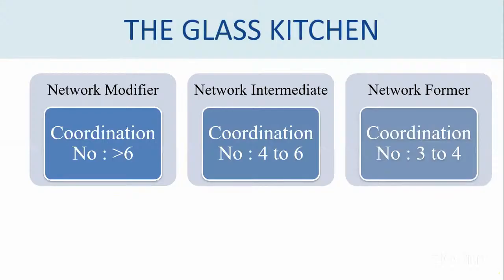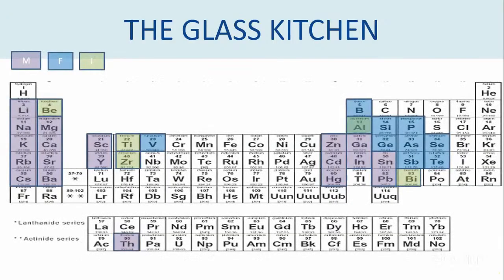So here, what kind of elements belong to the class of network modifier, and what kind of elements belong to the class of network intermediate, and which one belong to the network former? If it has the low coordination number, say per se boron, silicon, okay, they have a very low coordination number between 3 to 4, they fall into the category of network formers. High coordination number like alkali metals or alkaline earth metals, they fall into the category of network modifiers. Some elements like lead, zinc, they have a coordination number ranging between 4 to 6. They fall into the category of intermediate. So at the lower coordination number, they become like former, whereas at the higher coordination number, they take the role of modifier.